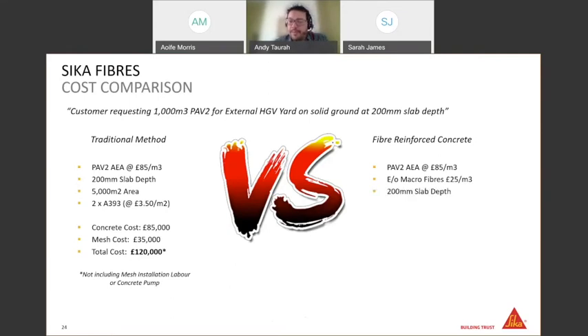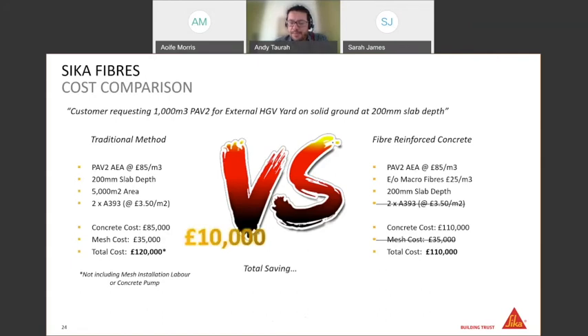The slab depth remained the same, 200 mil. However, we were able to remove the need for the 2 layers of the 393. So whilst the concrete itself had gone up to £110 per cubic meter, the mesh cost was completely removed. So just on a material basis only, there was a 10 grand saving.